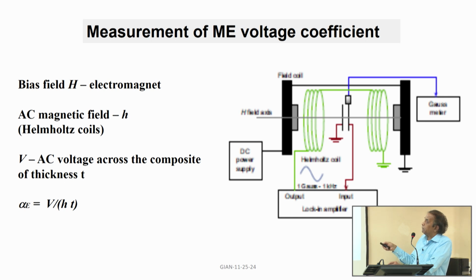Then the DC power supply will drive this electromagnet, and the AC power supply will drive these Helmholtz coils. Then you measure the voltage across the sample, the ferroelectric layers. There are many ways to measure the voltage. You can use an oscilloscope, or you can use a lock-in amplifier. A lock-in amplifier will lock onto a particular frequency. So that would eliminate any noise pickup. So if you know the frequency of the magnetic field you are applying, then you can lock the voltage measurement to that particular frequency. So it will give you a clean measurement. It won't have fluctuation because of noise pickup.